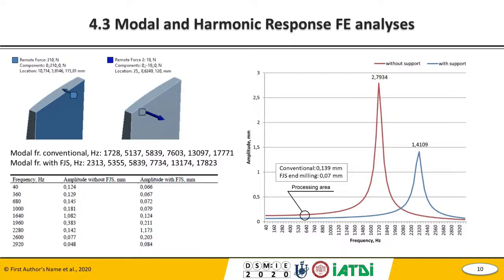So, modal and harmonic response finite element analysis. The main goal of the harmonic response analysis was to prove our assumption that by applying additional support, we not only decrease the amplitude of the oscillation under external cyclic load, but also shift the natural frequency of the structure. Consequently, we get more frequency space for the cyclic load without negative resonance impact.